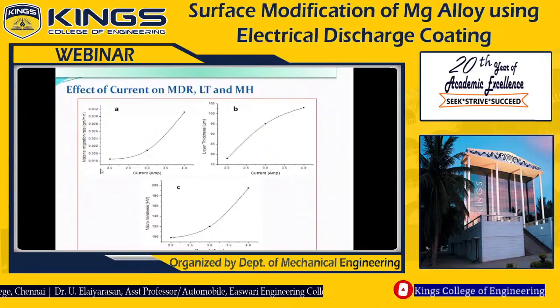Mainly, we should concentrate on the material migration rate. If the material migration rate is high, the layer thickness and micro hardness will be high. If the material migration rate is low, the layer thickness and the micro hardness will be very low. It's a basic concept.